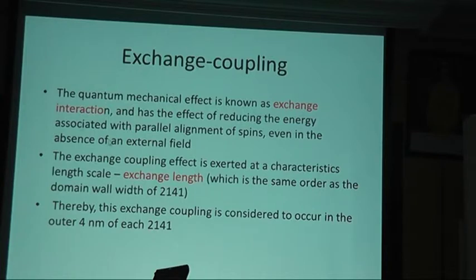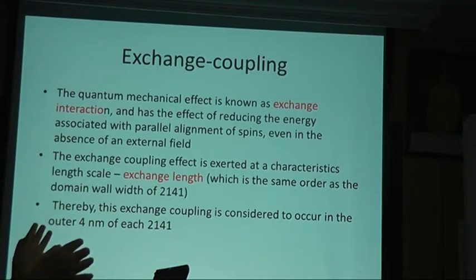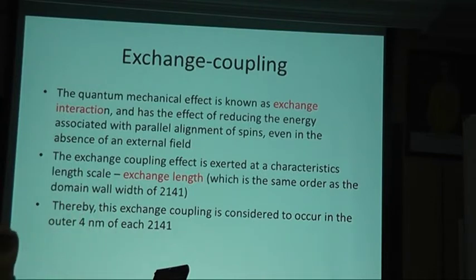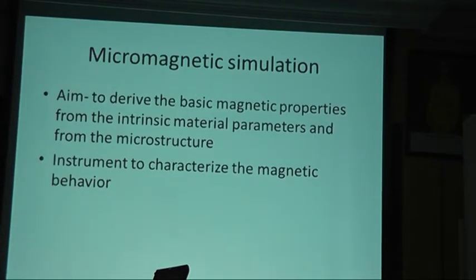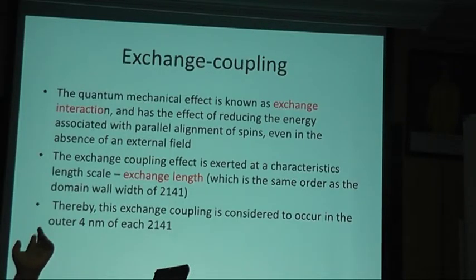The exchange coupling effect is exerted at a characteristic length scale, which we call the exchange length. Different materials have different exchange lengths. For 2141, the exchange length is about 4 to 5 nanometer. So the exchange coupling happens in that distance. There are a lot of methods to study exchange coupling.